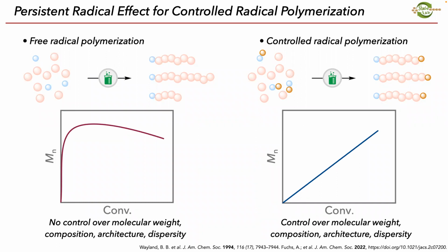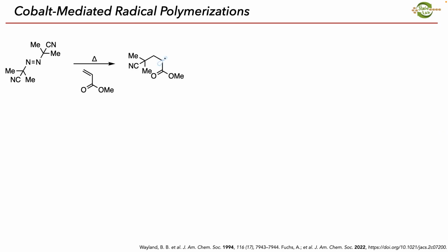And now we can do things like copolymerizations, we can control the architecture, and overall the molecular weight distribution, which is the uniformity of these polymer chains. And so in order to conduct this polymerization, we need to use a strategy of controlled radical polymerizations. And we turn to cobalt, which is a transition metal, which can reversibly deactivate propagating radicals.